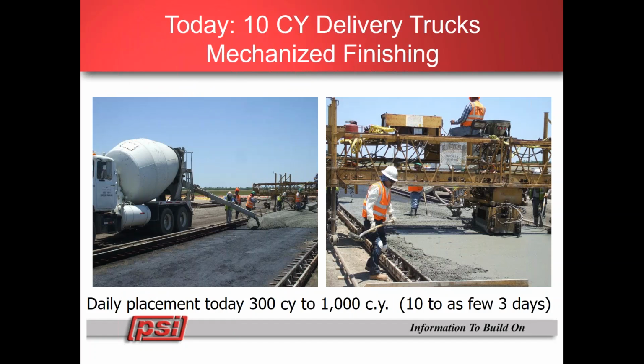Today, concrete can be delivered in 10 cubic yard ready-mix trucks. We have mechanical finishing processes. The daily placement of concrete can very readily achieve anywhere from 300 to 1,000 cubic yards today. So Belknap Place today could be placed in as few as 3 days or perhaps 10 days on average if we ignore intersections and other special considerations.